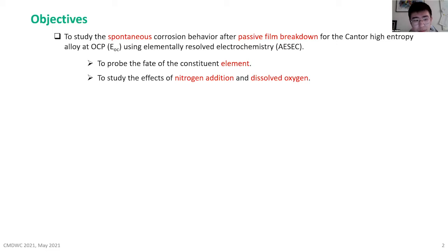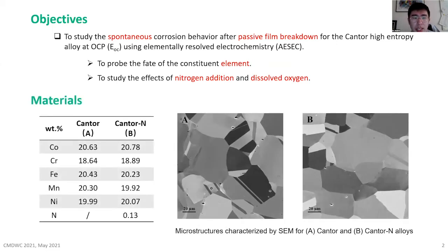dissolved oxygen. So the two alloy materials we were using are the Cantor alloy with equimolar ratio of cobalt, chromium, iron, manganese, and nickel, and the other one, where we add 0.13 weight% of nitrogen into this alloy. On the right-hand side, you will see the microstructure of these two alloys. It shows that the nitrogen addition did not significantly alter the microstructure.